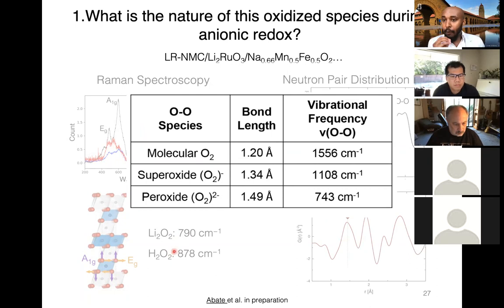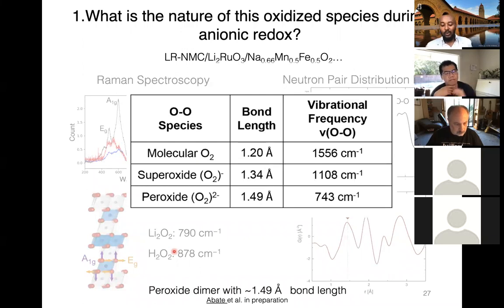And this wave number that I measured from the Raman spectroscopy is also very similar to the peroxide species. So what we would like to argue here is that when we have anionic redox, we form an oxygen-oxygen dimer with a short bond length.